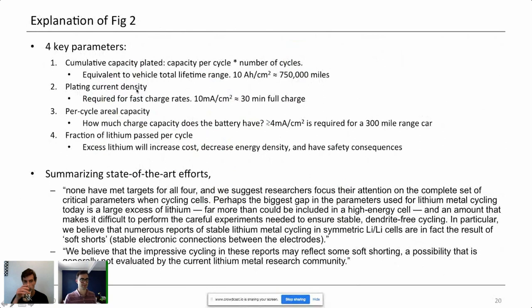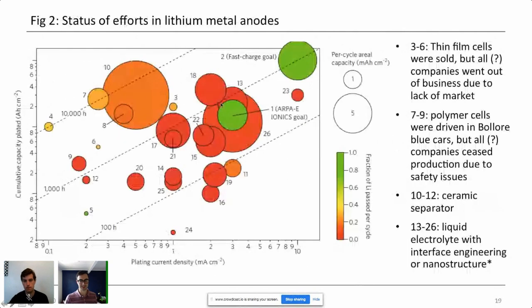The x-axis is the plating current density. Again, that's required for fast charge. This number of 10 milliamps per square centimeter over here, that's their fast charge goal, would enable roughly a 30-minute charge. I think that's not sufficient to get real mass market adoption. I think you probably have to get it to more like 15 minutes or less charge time, so that people who are considering what car to buy know it has to be able to take me on road trips and take me out skiing and basically cover all my use cases. I think getting the charge time below 15 minutes is going to be very important for most consumers.